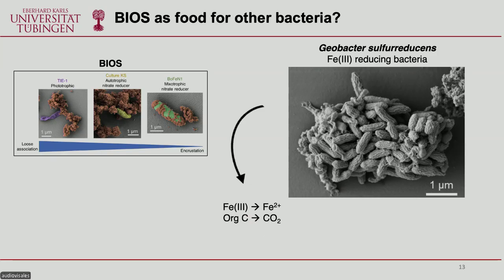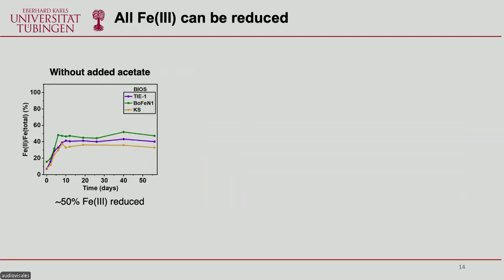And so in our experiments, we simply make these biogenic iron oxyhydroxides, and then we feed them to Geobacter sulfurreducens, and then we see what happened. In the first experiment, we did not add any extra organic carbon, but we can track the amount of iron 2 that is produced relative to the total in the system. Then we tracked this over 50 days, and we saw that only about 50% of the iron 3 can be reduced, which means that the iron has been transformed.